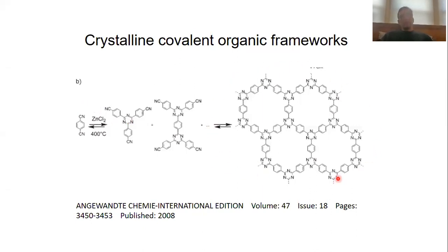So this is true for this class of triazine covalent organic frameworks. So even though there have been intense efforts made to make many other structures of this kind, because they're attractive due to their chemical stability, to my knowledge, this is the only case in which this has succeeded. So this is, to my knowledge, still the only example of a crystalline triazine-based covalent organic framework. It's not so difficult to make amorphous ones with other building units.